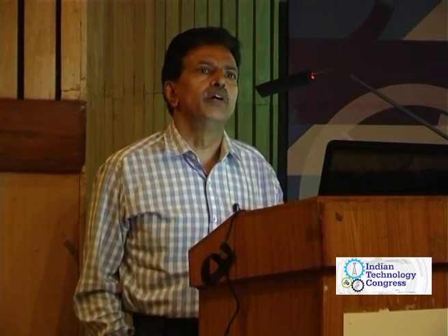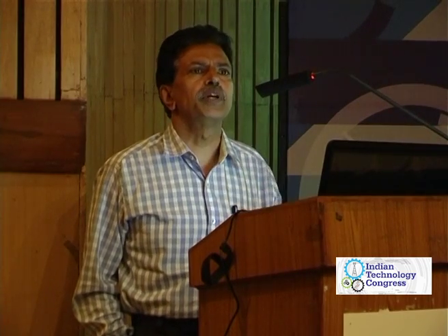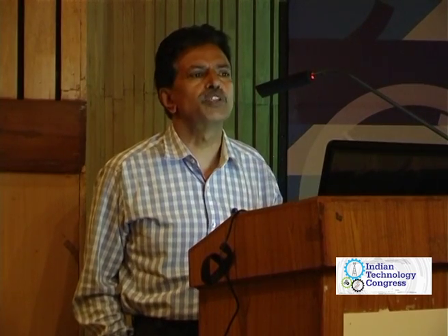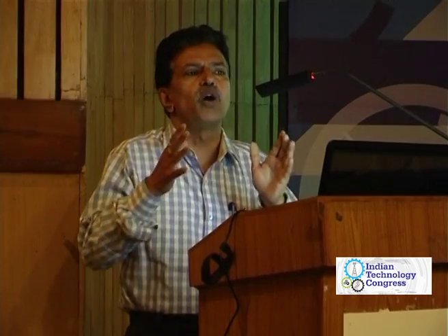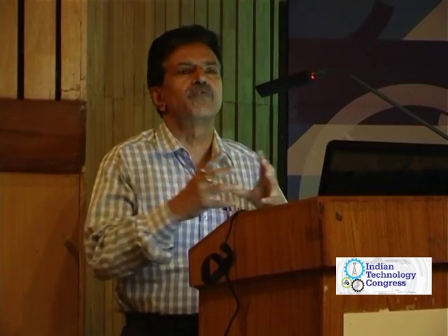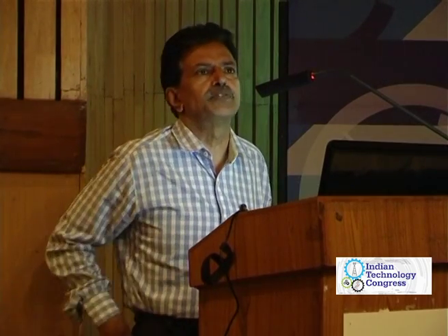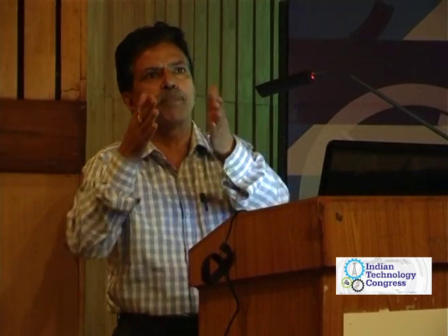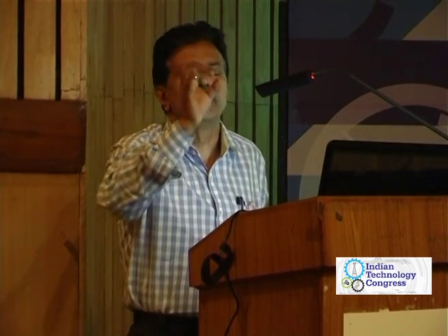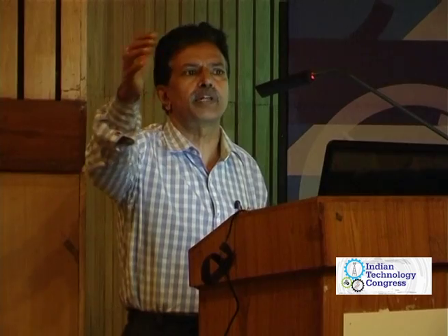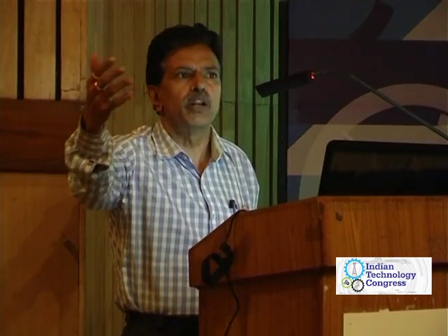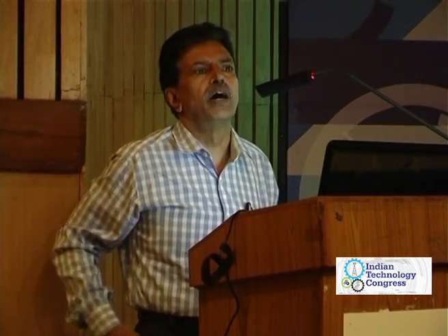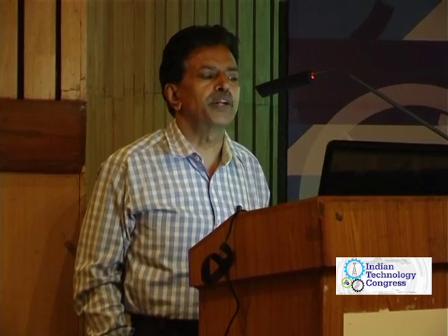When looking at EDM and so on, there is going to be damage to the reinforcement. Once there is a pull out of the particles or pull out of the reinforcement fiber, whatever the damage we are talking about, there's always going to be a deviation in the dimensions. There is going to be a bit of tapering. You're talking about micron level: it may be 100 microns, and that can be around 98 on the other side. So there's going to be a tapering. That's one major problem that we need to address.